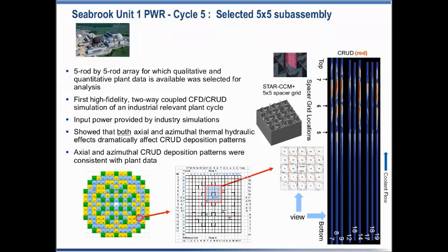This was done a couple of years ago. At that time, we just used input power distributions rather than driving them from the neutronics code itself. So this was really just a coupling of the thermal hydraulics and the crud and chemistry code. But we could see both the axial and the azimuthal variation in crud deposition, which is very similar to the observed crud we could see on the Seabrook fuel assemblies when we did the examinations there.